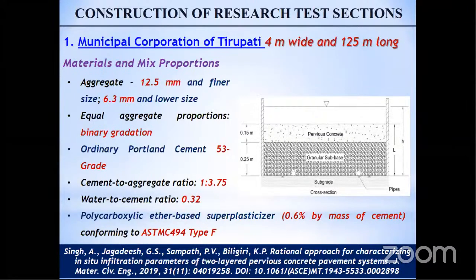By binary aggregate gradation, what I mean is that two aggregate sizes were used. One was 12.5 mm in larger sizes, and the other one was 6.3 mm in finer sizes. These two aggregates were blended with ordinary Portland cement in equal proportions to create a binary gradation. The cement to aggregate ratio was about 1:3.75, and the water to cement ratio was about 0.32. Further, a superplasticizer was used in order to enhance the workability of the mixture. The results of the study are also published in one of the international journals, Journal of Materials in Civil Engineering, which you can refer to for further information.